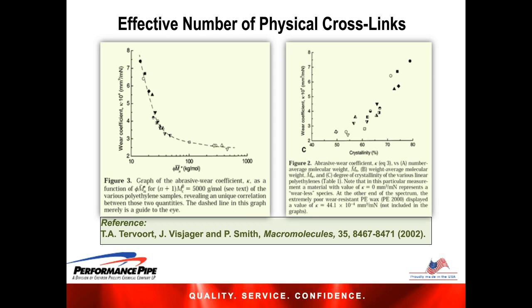So the left chart basically shows that the wear rate decreases as this phi mn star product increases, and this product is basically a reflection of the number of physical crosslinks. In other words, as the number of physical crosslinks increases, the wear rate decreases.